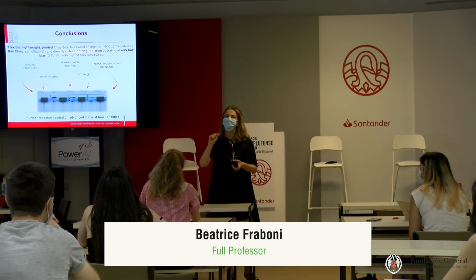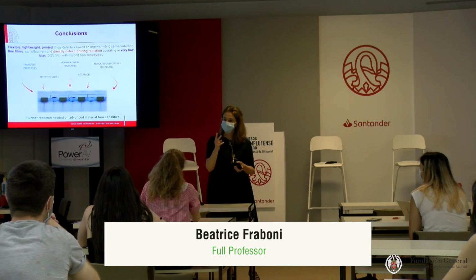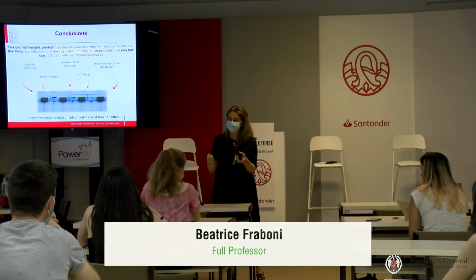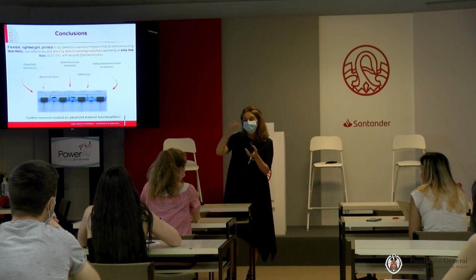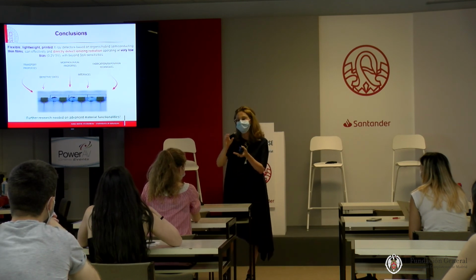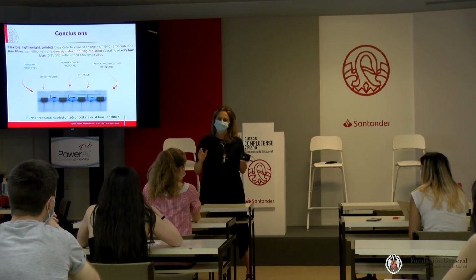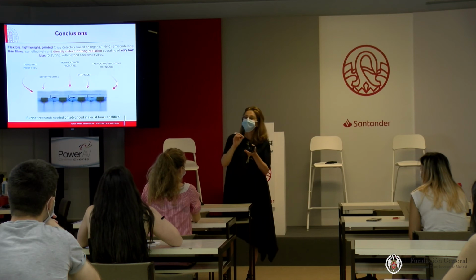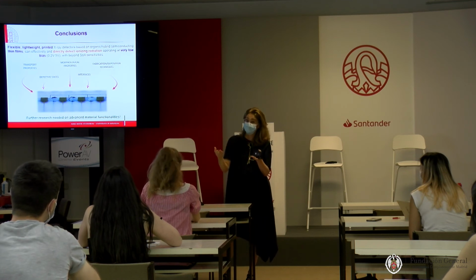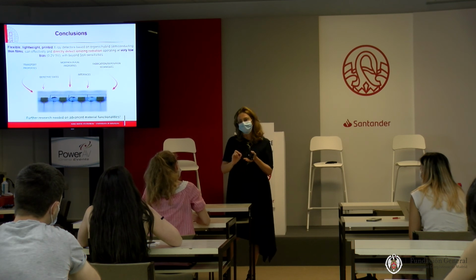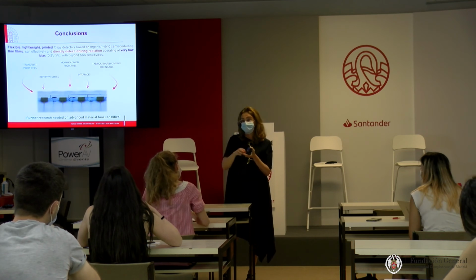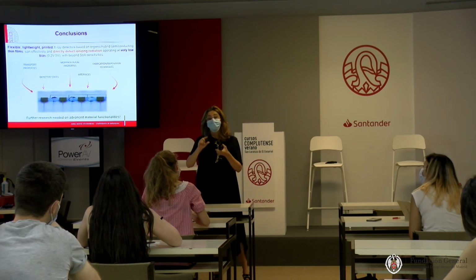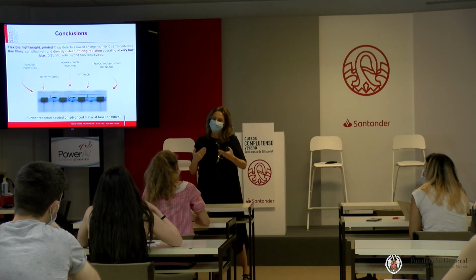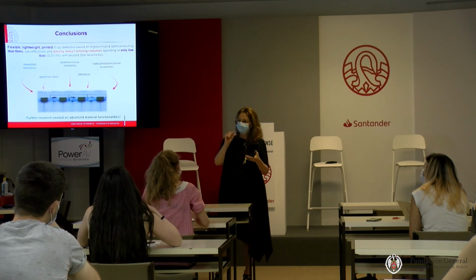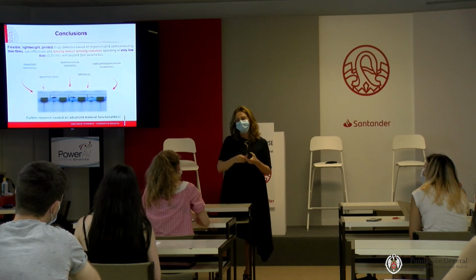The dielectric should not be too thick, for two reasons. First, because you want to maintain flexibility. And second, because you don't want it to stop too much of the radiation. So typically the dielectric thickness can be 10 nanometers. They're really thin layers, made of a material like parylene, which is another organic material, or aluminum oxide, which can be sputtered or deposited by solution, but they are very thin. You don't want them too thick, otherwise you will need to apply even higher voltages to operate the device. So you need thin for low operating bias, flexibility, and no radiation stopping.